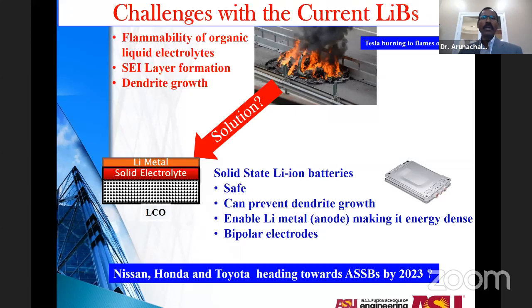In fact, the motivation for the development of solid-state batteries comes from the challenges and issues associated with the currently available lithium-ion batteries. You can see an automobile going into flame, mainly because the solvent is an organic solvent with a relatively lower flash point. So, mostly a safety aspect. And the liquid electrolytes also need a separator, which is typically a polymer membrane of maybe 20-25 micron thickness, that could allow lithium to grow into a needle shape to physically short between the anode and cathode if you have to use lithium.